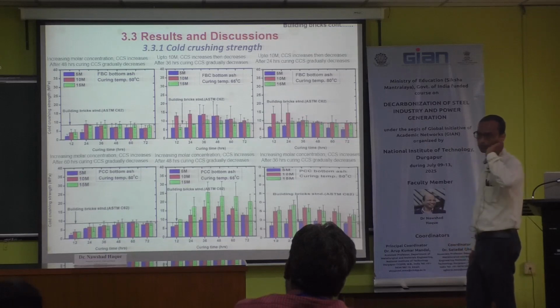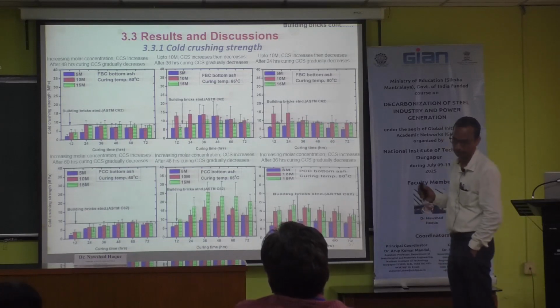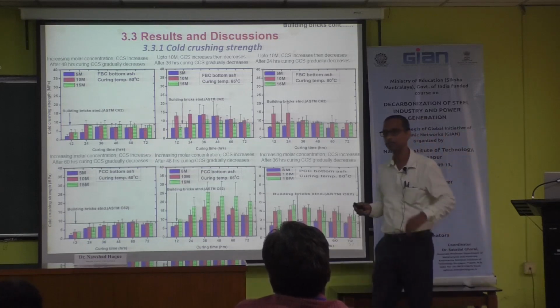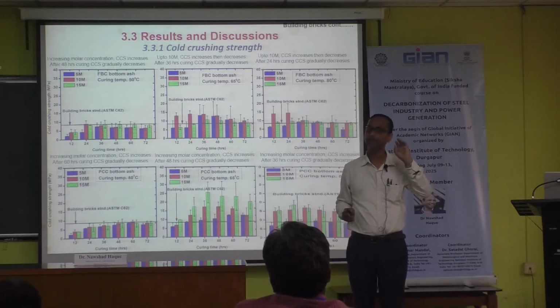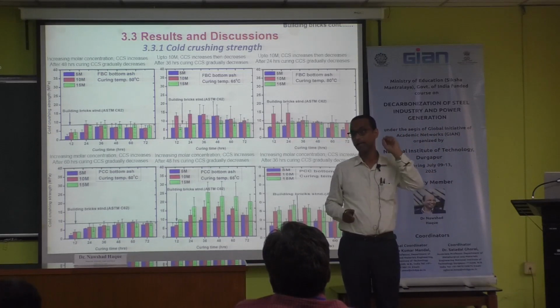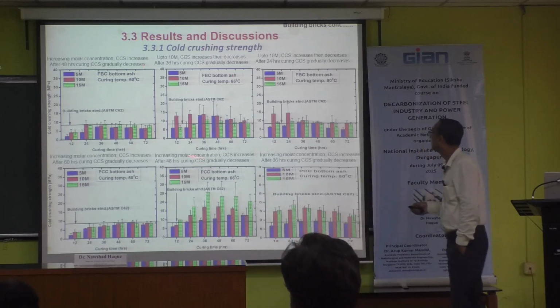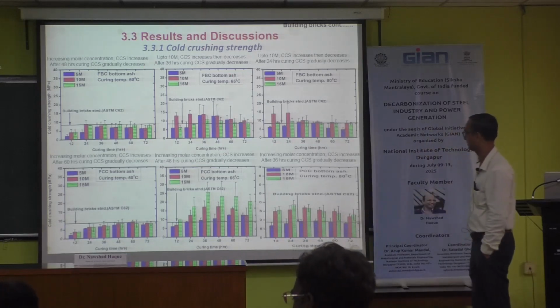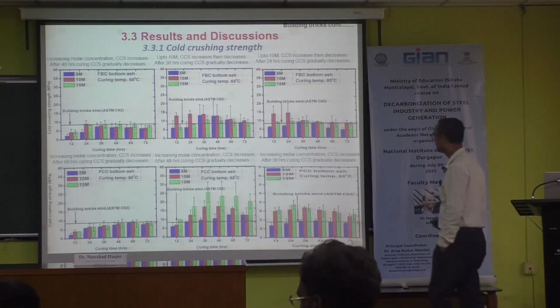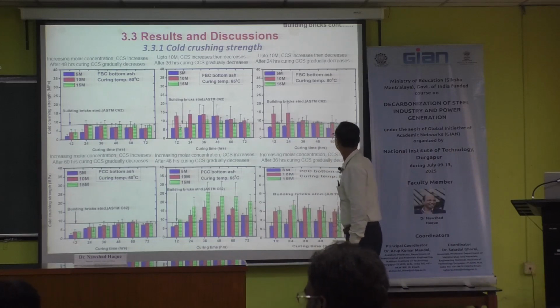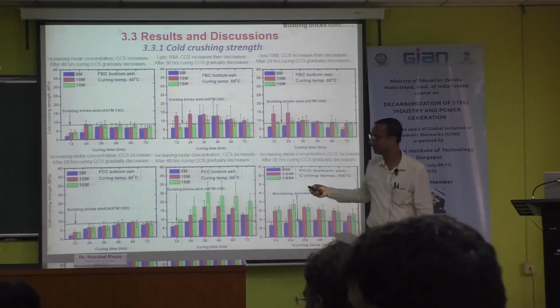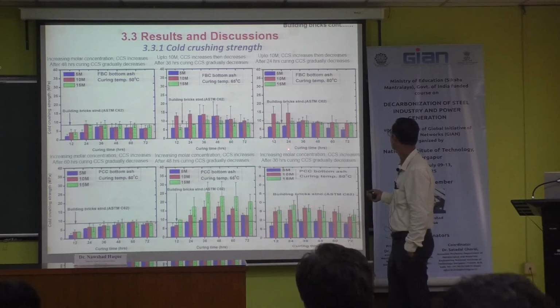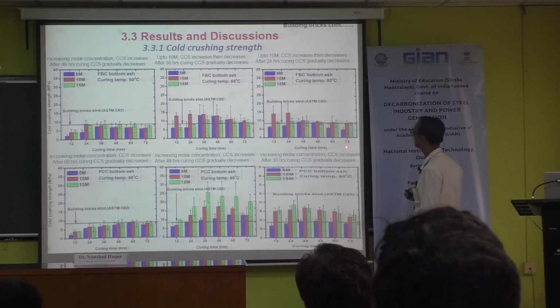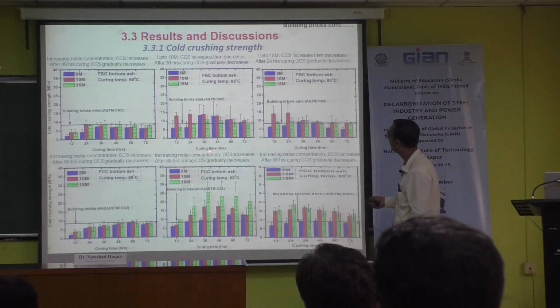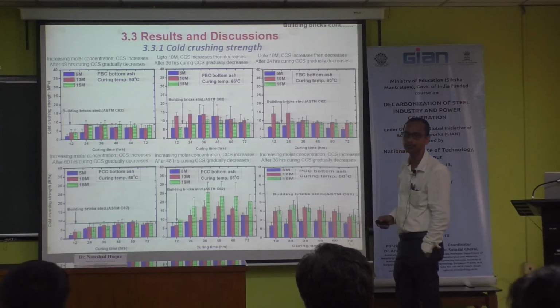Therefore, temperature should be optimum, so 65 degrees was the optimum in our case, because it will vary case to case, because the chemical composition of the ash may be different, the concentration of the alkali may be different, the activators may be different. Therefore, in our case, we have simply 65. If you see, if you cure for up to 72, it is curing time in hours, 72 hours. And you can see here you are getting similar strength up to 48 hours also.